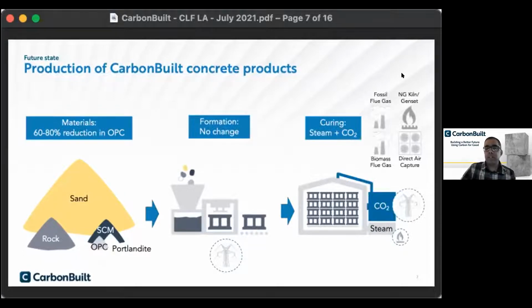So first I'll say the steam curing that happens here is a shortened steam curing cycle. We have less Portland cement in the mix, so we need less steam to get the hydration going. But then following the hydration with steam, we're curing with CO2. And as I said, there's three differences relative to what others have tried before that makes our process low cost.